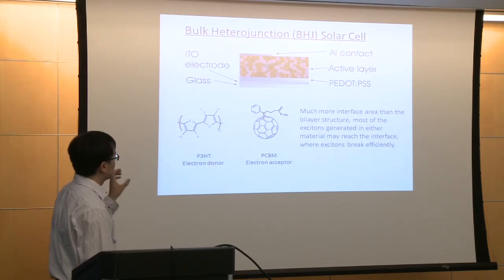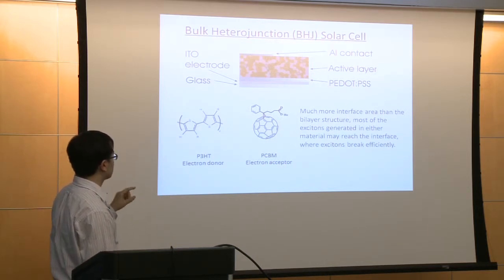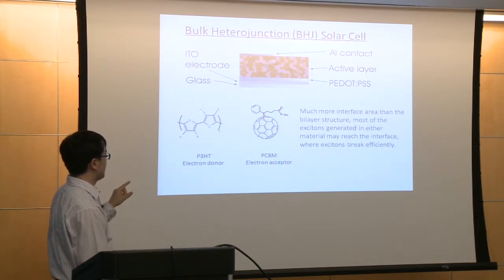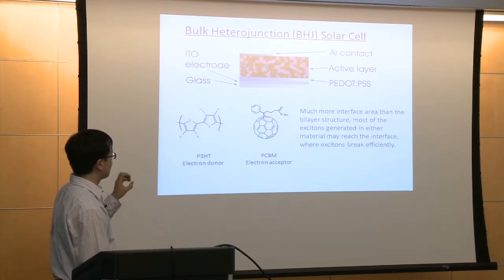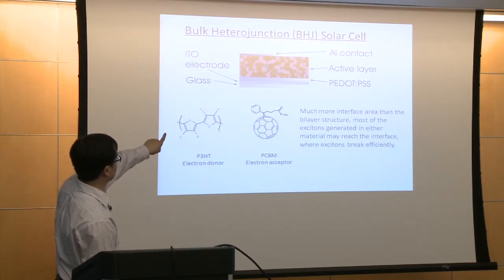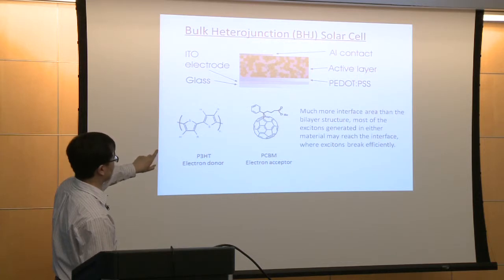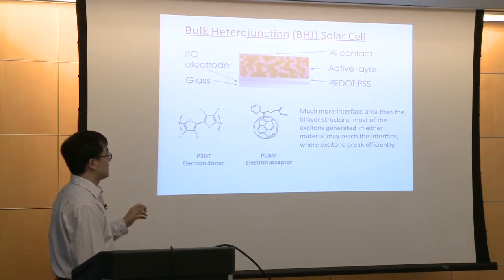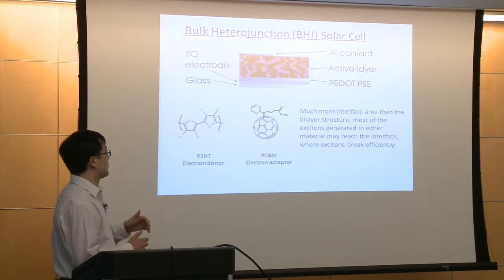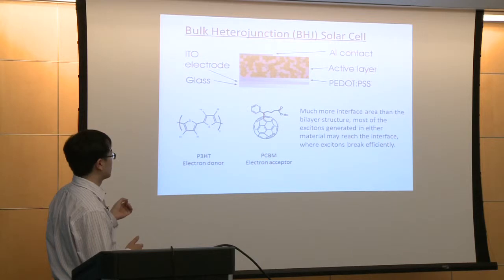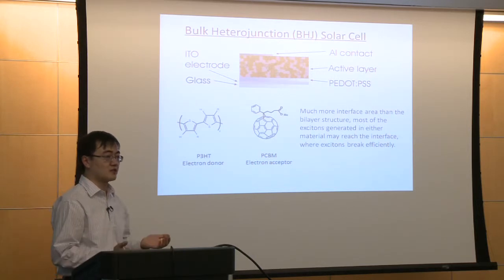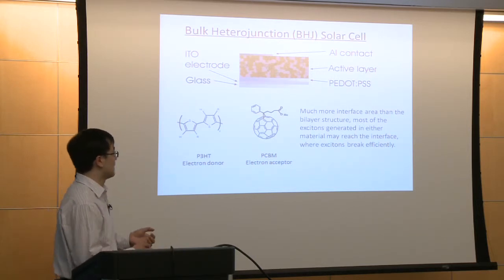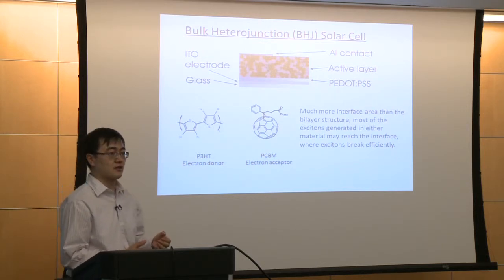So basically, the difference between the bulk heterojunction solar cell and the bilayer organic solar cell is that scientists blend the electron donor and the electron acceptor material together. They mix them together as one layer. So you can see there are different domains in the active layer for the electron donor and for the electron acceptor. In this case, there is much more interface area compared to the bilayer organic solar cell. And most of the excitons generated can reach the interface, then can be efficiently separated into electrons and holes. So this can greatly enhance the efficiency of the solar cell.